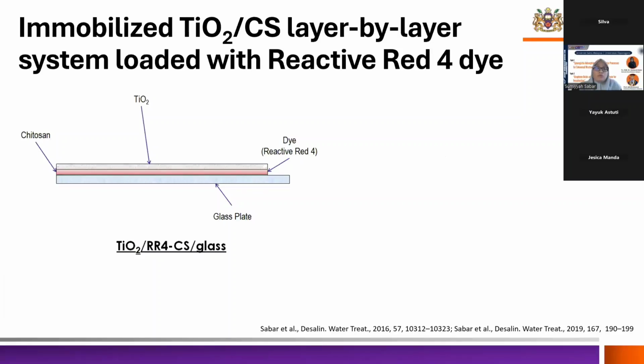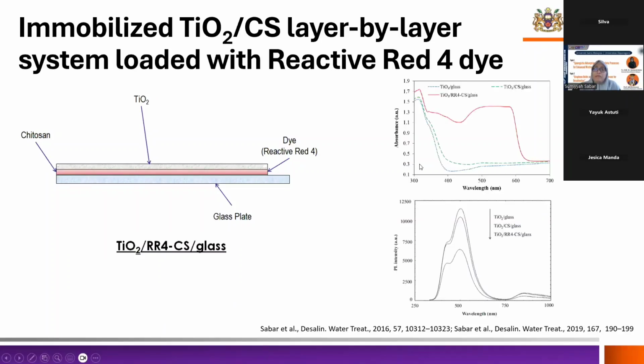So after that, we want to confirm whether the adsorbed dye really contributes to the charge transfer, really contributes to the enhanced photocatalytic activity. So in this case, we try to mimic it, we use Reactive Red dye as a photosensitizer. Okay, so we have a similar setup. Now we fully adsorb this chitosan with Reactive Red 4 dye, and then we coat it with titanium dioxide. So this is TiO2 Reactive Red 4 chitosan glass. And we observe that there's a shift in the visible light region due to the presence of the dye. And in fact, for the photoluminescence analysis, we also observe a decrease in the intensity of the PL peak. So this indicates that the recombination rate of the electron is lower in the presence of the dye.